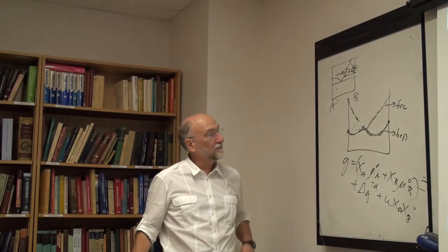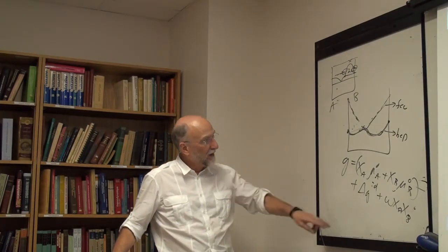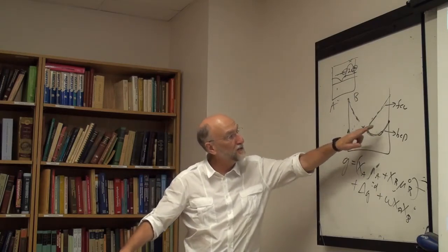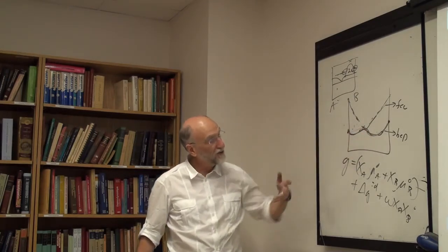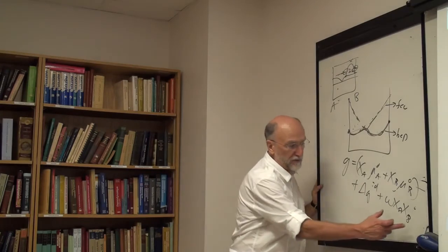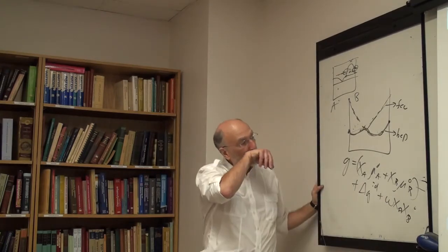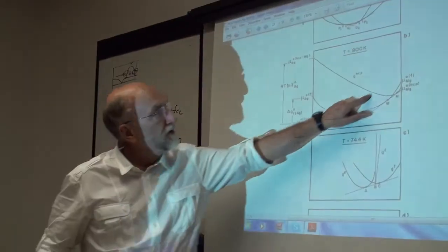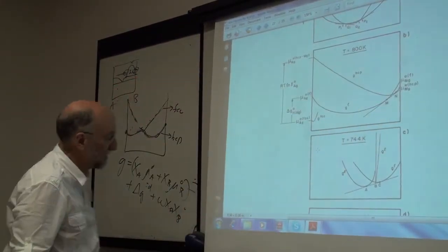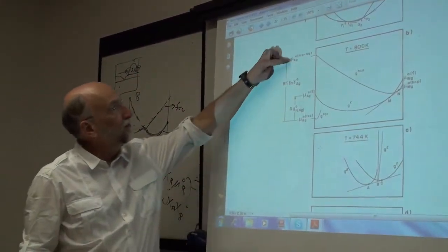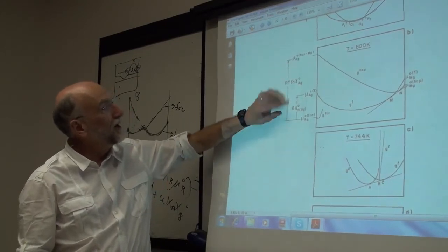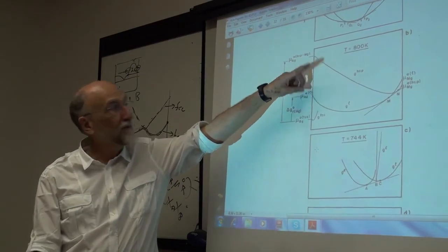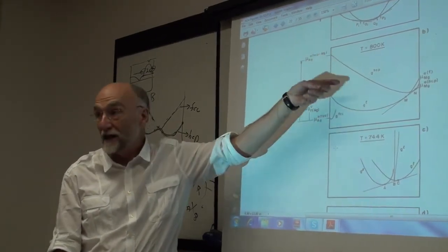However, this equation here now, if they're the same structure, which is always the case in a liquid, you now have fewer adjustable parameters. When I did it before, I rubbed it off, but you had this equation here and you had this equation here. We had the term mu silver HCP minus mu silver FCC. That was one adjustable parameter, and your regular solution term omega was a second parameter.